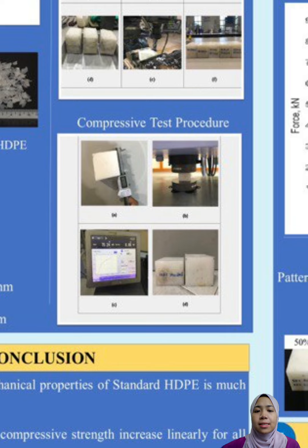Next, for the compressive test procedure, a compressive strength test was carried out in the structural laboratory in UPNM. The machine used is the UTM machine. The specimen was prepared as described in the standard. Next, the sample was placed between the compression platens, ensuring it was aligned with the center line of the platen. Finally, the test was stopped when the sample was compressed by 30% of its height. The force and deformation data were recorded.